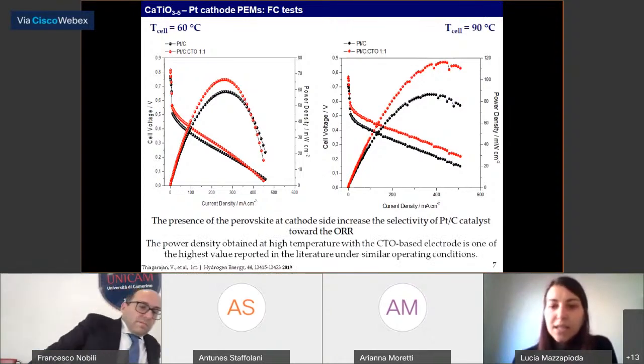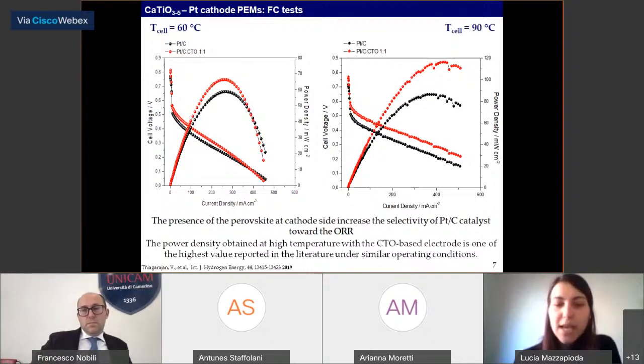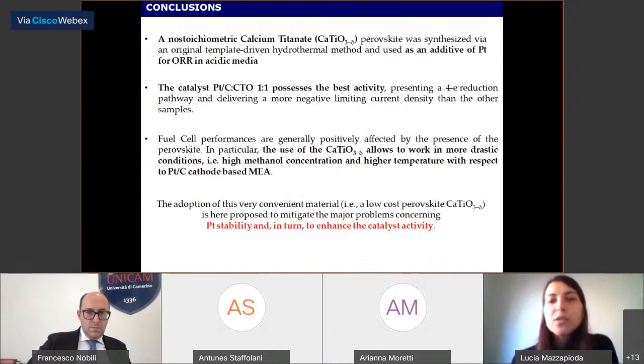Furthermore, at 90 degrees, the maximum power density obtained is one of the highest values reported in the literature under similar operating conditions. Concluding, a non-stoichiometric synthetic perovskite was synthesized by a hydrothermal method and used as an additive of platinum for the oxygen reduction reaction. Among all the samples investigated, the catalyst platinum-carbon plus perovskite 1:1 has shown the best activity, and it was used at the cathode side of the direct methanol fuel cell.